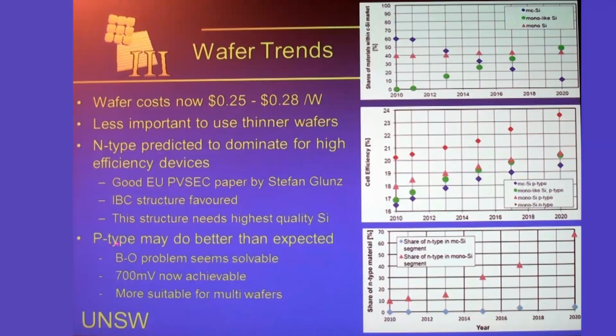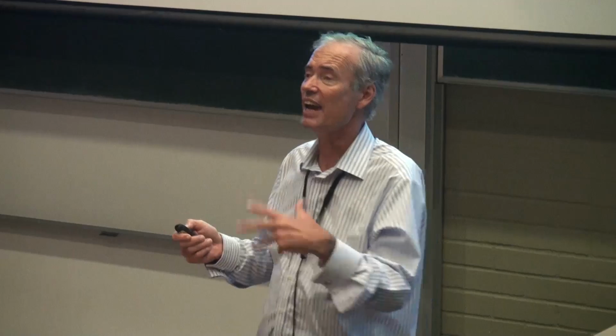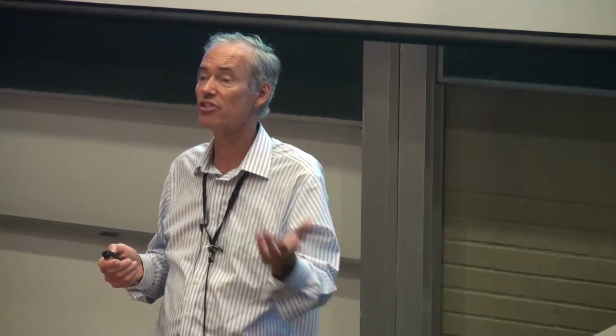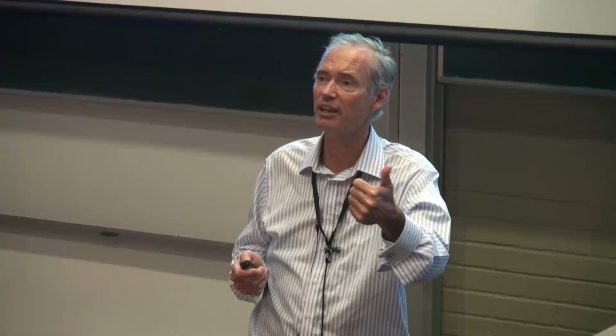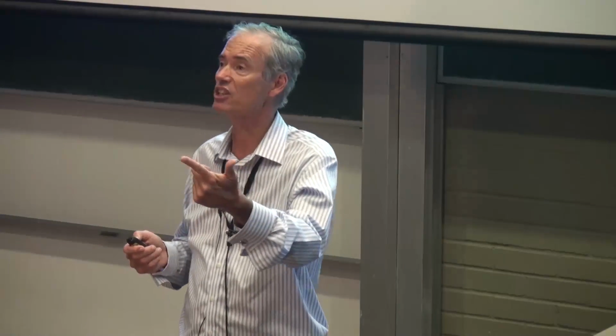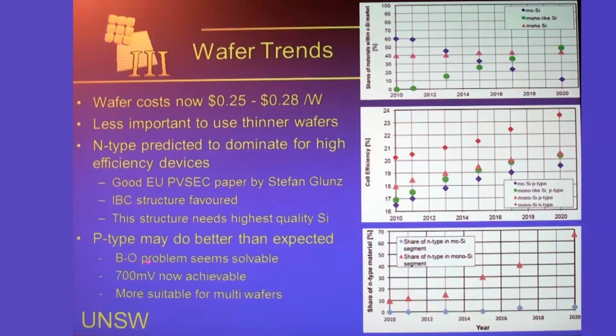One of those is the fact that I think P-type wafers will do better than what people have expected. See, the main difference is the boron-oxygen defects. The N-type mono doesn't suffer from boron-oxygen defects. P-type Czochralski does, because it's got boron as the dopant. You get oxygen inevitably in the crucible when you're growing the Czochralski wafers. The boron-oxygen defects degrade the quality of the wafer. But I think there's good evidence now that this problem is solvable. So we have developed one technology here that we believe clearly solves the problem. There were a couple of other papers at the conference that also claim that they've found solutions to the boron-oxygen defects. There's actually been a lot of work done in recent years, some very good work done at Konstanz University about something like 5 years ago, where they partially came up with a solution to solving or eliminating some of the boron-oxygen defects.